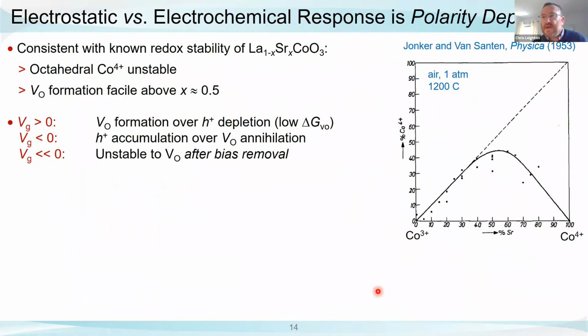But before I do that, I just want to point out that that preliminary conclusion is completely consistent with the known redox stability of this and many other magnetic oxides, right? So we're dealing here with cobalt 4+. It's been known since the 50s that this is very unstable towards the formation of oxygen vacancies. The material is primed to form oxygen vacancies. So when we put on positive voltage, we have the electric field oriented in the right direction to remove a negatively charged oxide ion. And that's exactly what happens, aided by the low enthalpy of formation of the oxygen vacancies.